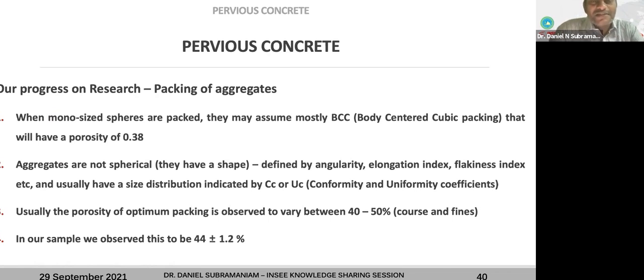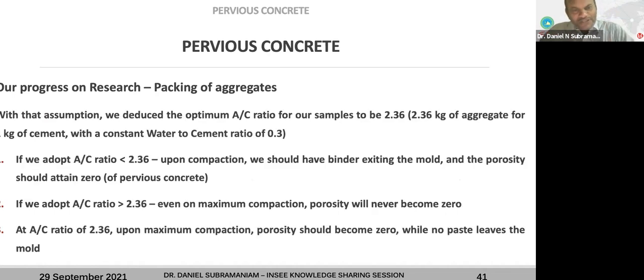The aggregate shapes and size distribution are actually well defined in geotechnics. So we use these parameters a lot in geotechnics. In our experiment, for the aggregates that we used, the porosity is about 44 plus or minus 1.2. Based on that, we calculated the optimum aggregate to cement ratio to be 2.36 for our studies. So anything more than 2.36, you will never be able to get zero porosity. Anything less than 2.36, no matter how much more you put in, with compaction, it's going to come out.